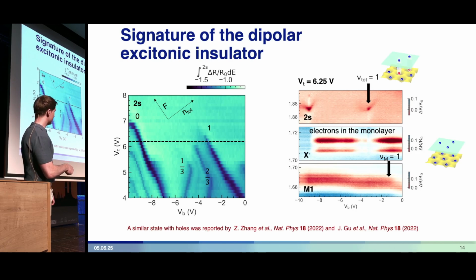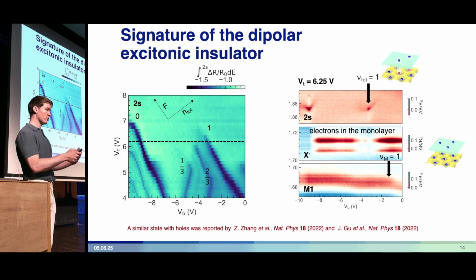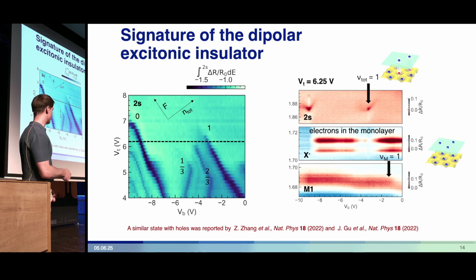And curiously, if we look at the kink in the M1 Moiré exciton, you can see that now this no longer aligns with the overall incompressible phase, and that's because this is a distinct phase now. It's a Mott insulator living underneath some uncorrelated electrons in the monolayer, which you can see from the existence of trions at that same gate voltage.